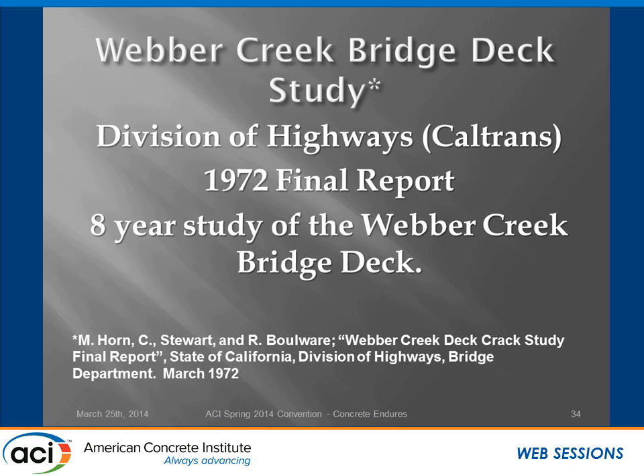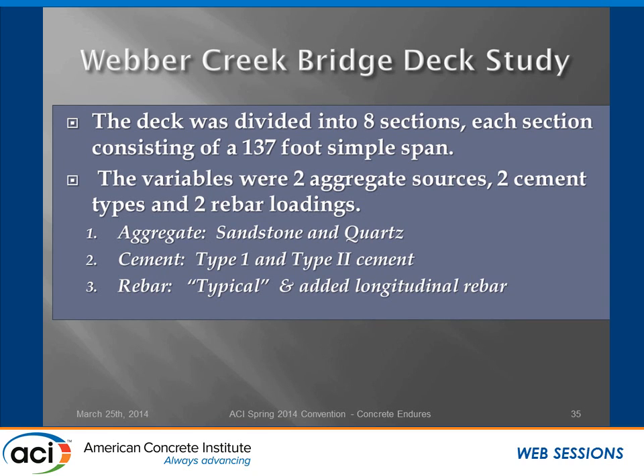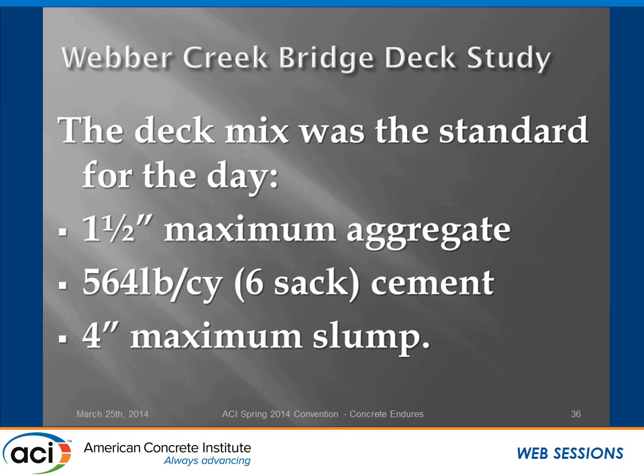To evaluate, Caltrans performed and finalized a report in 1972 on the Webber Creek Bridge, which is just east of Sacramento. Eight years were put into that study. This bridge was divided into eight sections of 137-foot simple spans, and that allowed us to evaluate three variables: aggregate, cement, and rebar. We used two aggregates, one sandstone and one quartz. We used type 1 and type 2 cement, and we used the typical deck reinforcement of the time, and also a more beefed up reinforcement strategy that had additional longitudinal reinforcing steel. The deck concrete was the deck mix of the day: 1.5-inch maximum aggregate, 6-sack mix, and 4-inch maximum slump. Notice it hasn't changed much.